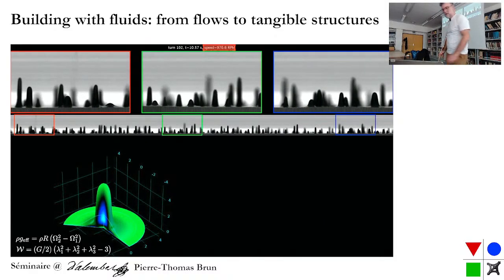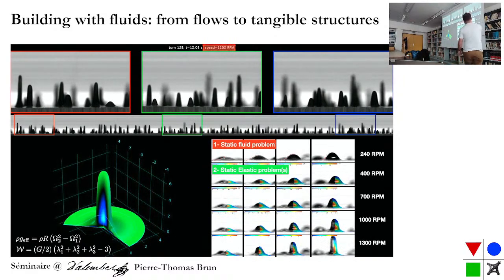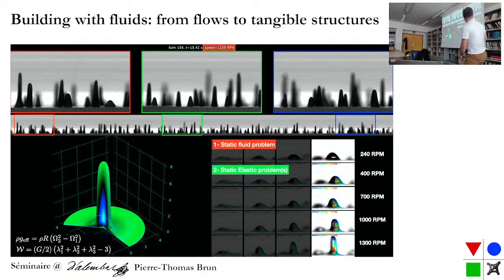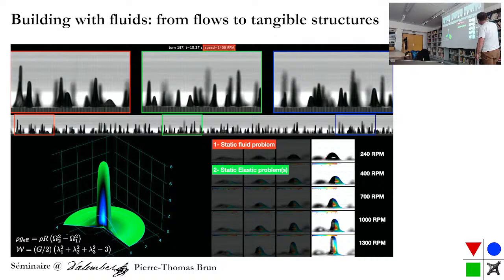This is too busy, so forget about that. Just look at this one. So this is a drop. The red dotted line that you barely see is actually the integration of the pendant drop equation. So we have a pendant drop. And then as we increase the rotation speed, we're going to stretch this shape. And then we find eventually this thing. And so I superimpose here the results of these finite element simulations for a static problem. And so you see that essentially it works well. So that's my justification for why I don't want to worry about viscoelastic effects or anything dynamic.